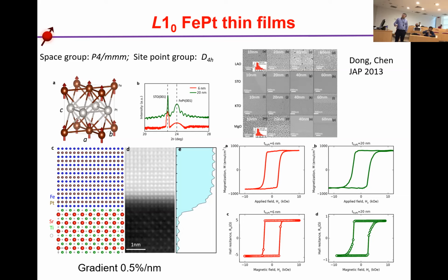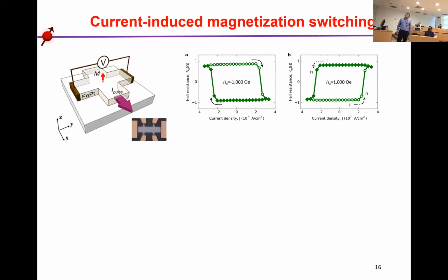In this case, the L10 film has a special structure, in which an atom layer of platinum and an atom layer of iron are alternately stacked along the Z direction. We choose a gradient of 0.5% per nanometer, and the films still show very good perpendicular anisotropy. And we make the device. Here we still apply a longitudinal field in the current direction. When we apply the electric current, we can switch the magnetization from up to down, and reversing the electric current, we can switch from down to up.